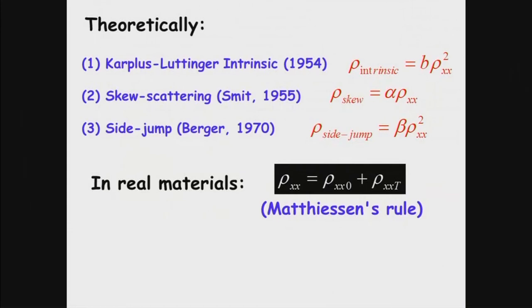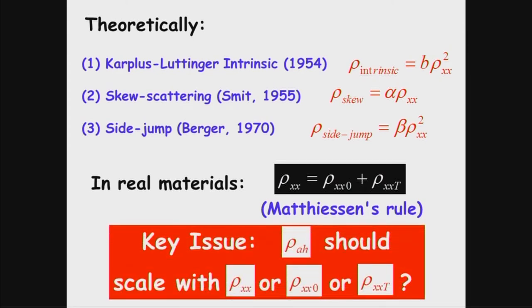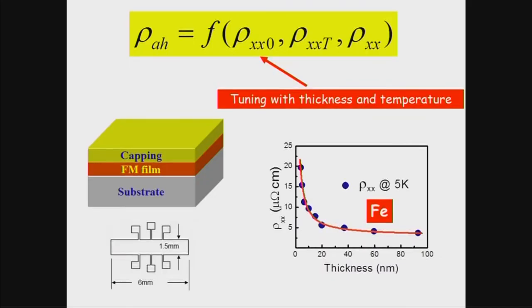And remember that all the theoretical model is just based on one kind of impurity in a periodic lattice background. But in real material, we have at least the lattice imperfection and the phonon contribution for the resistivity. So the key question to be asked is whether this scaling should go not only with this one, but probably also with this one and with this one.